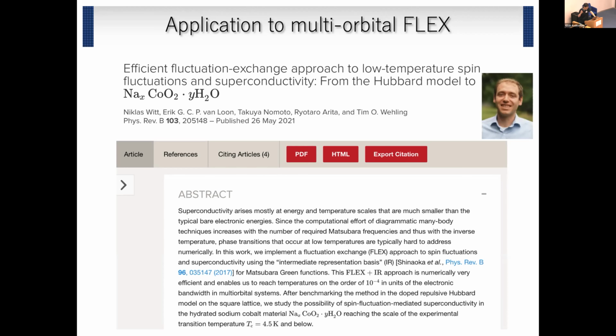And about 20 years ago, together with Kazuhiko Kuroki, I proposed that maybe f-wave superconductivity is realized in sodium cobaltate. But at that time, the numerical cost to solve the multi-orbital Hubbard model was very expensive, so we just calculated the eigenvalue of lambda at high temperature. But if we use the techniques of intermediate representation of the Green's function, here Niklas, the student of Tim Wehling, calculated the eigenvalue at temperatures of the order of 1 Kelvin.